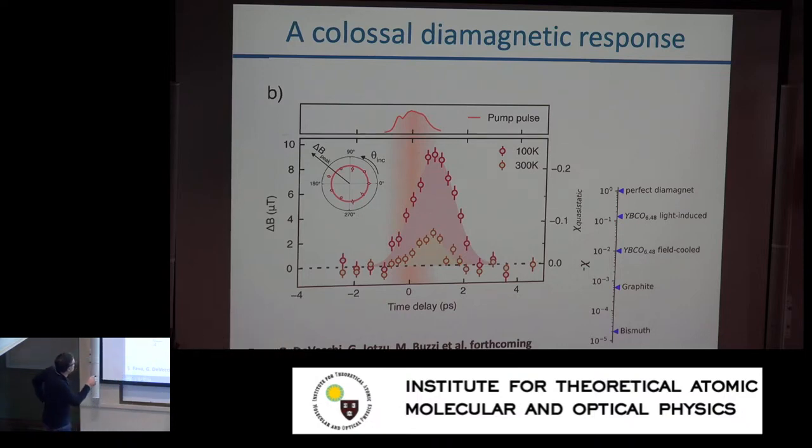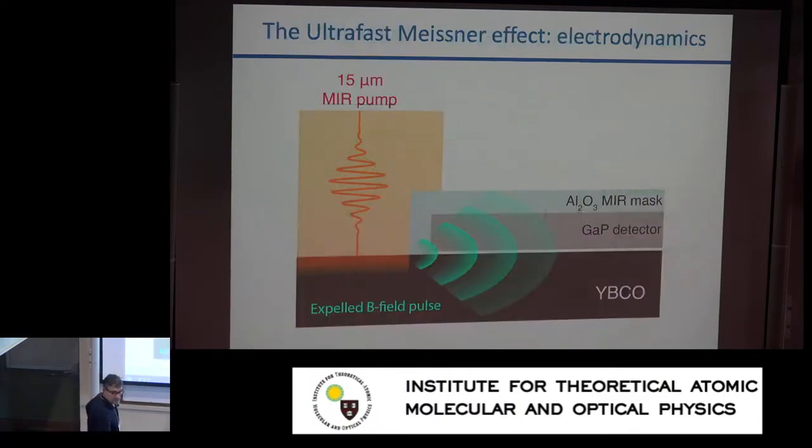You can also do all sorts of checks. You measure polarizations, and you show that because this is a Meissner effect, it cannot have lobes. You don't want to be measuring Pockels effects or various nonlinear optical phenomena. This needs to be isotropic. Anyway, we can discuss the details. You are basically doing the experiments by chopping multiple things. You chop the magnetic field, you chop various pumps, there's a number, and so you can identify the right response.